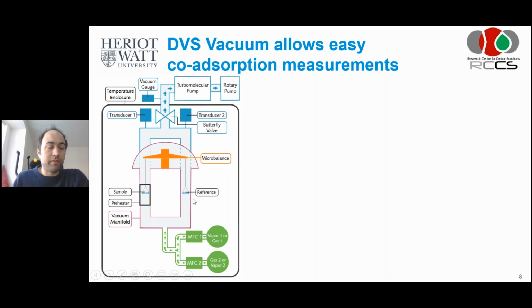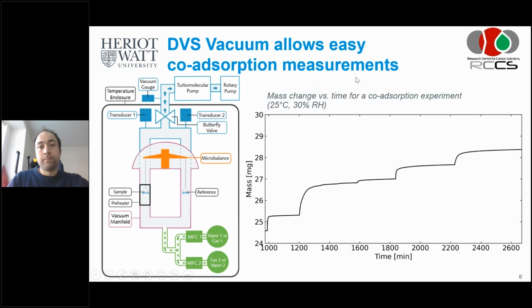Now, just very quickly on the DVS, you have two gas or vapor flows that flow into the system, here represented in green in the bottom of the graph. Then you have a sample pan where you have your sorbent sample. You have a reference pan to correct for any buoyancy that might happen. And then you have a microbalance here that measures the weight of the sample in your pan. Then the pressure is controlled by how much you flow, and by a butterfly valve that is located behind the sample. And then there's a vacuum pump that helps maintain the vacuum that you want. And you can operate this system in the simplest configuration between 25 and 70 degrees C. So this is what we've done.